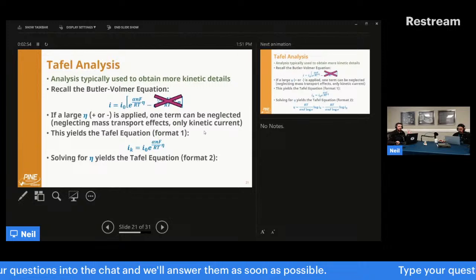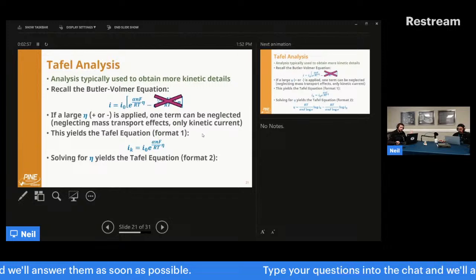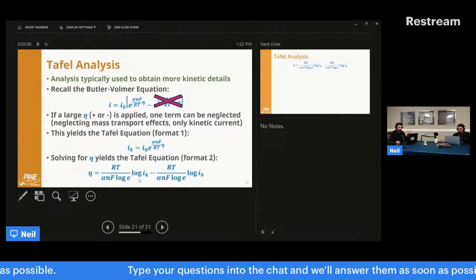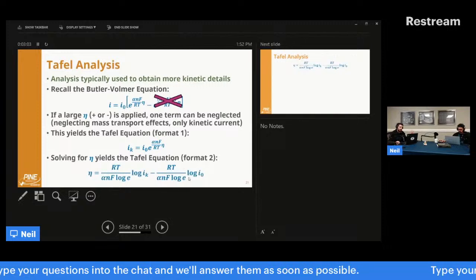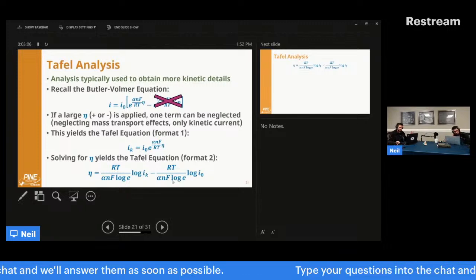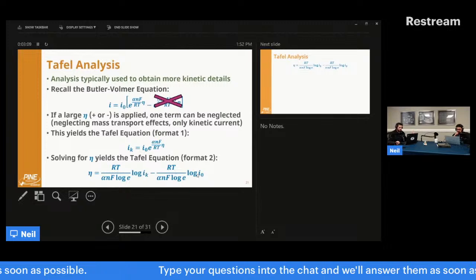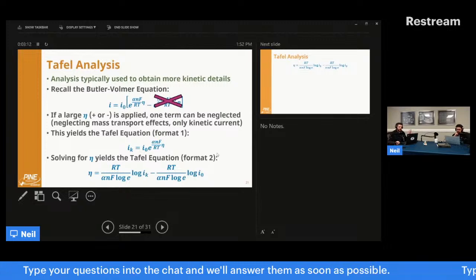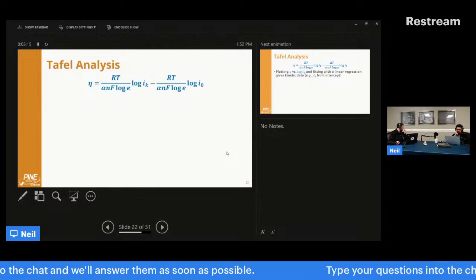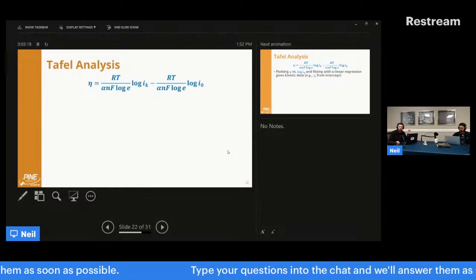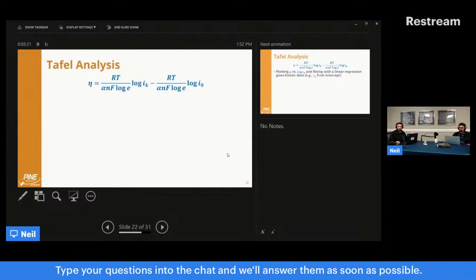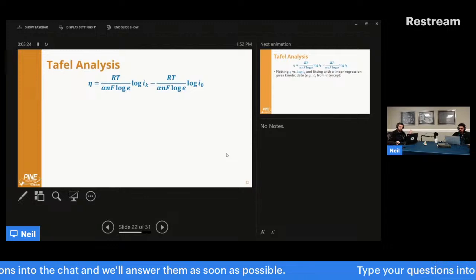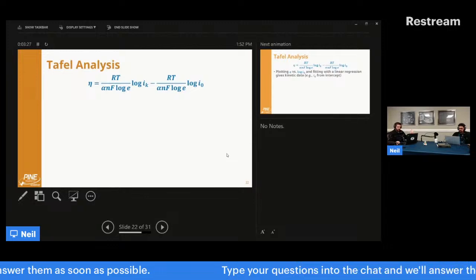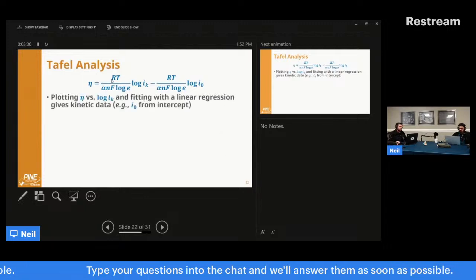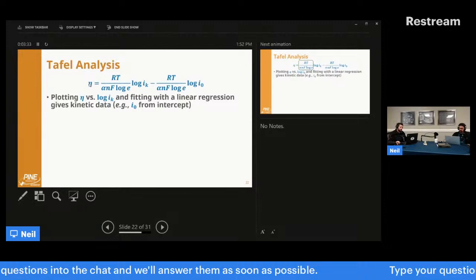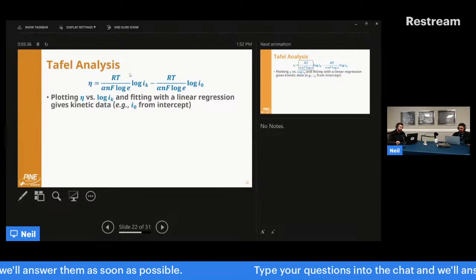So to get the Tafel equation in a form where the Tafel slope is usable, we take the natural logarithm of both sides, or the log base 10 of both sides, however you look at it. When you do the log base 10, you end up with the log of e, because we typically have decades of current. It's just easier than natural log. So we do log base 10 because it's easier to conceptualize. Okay. So the Tafel slope comes from the plot of overpotential versus the log of the current.